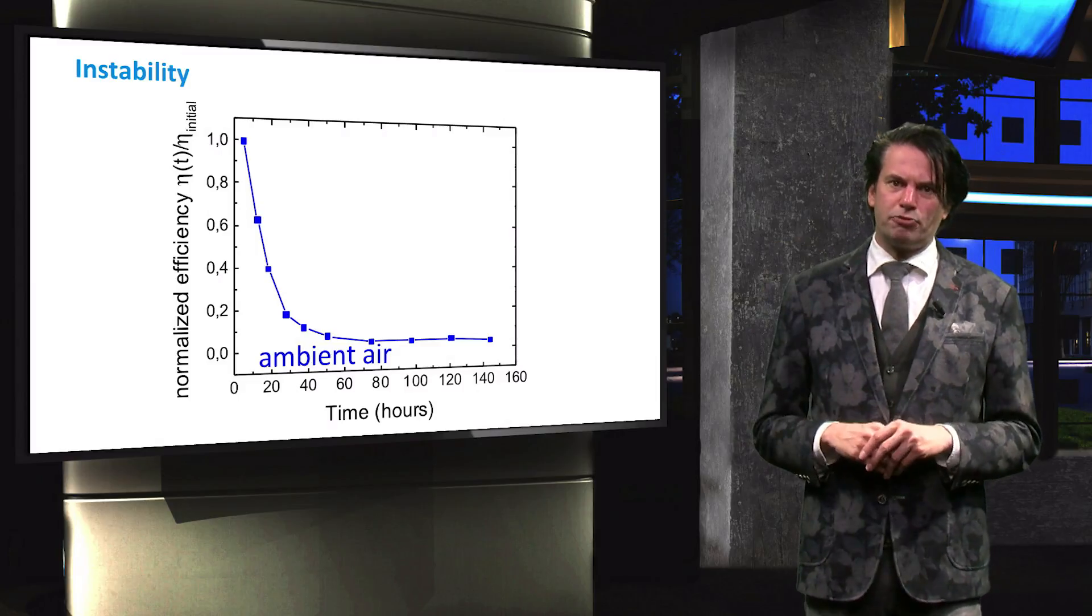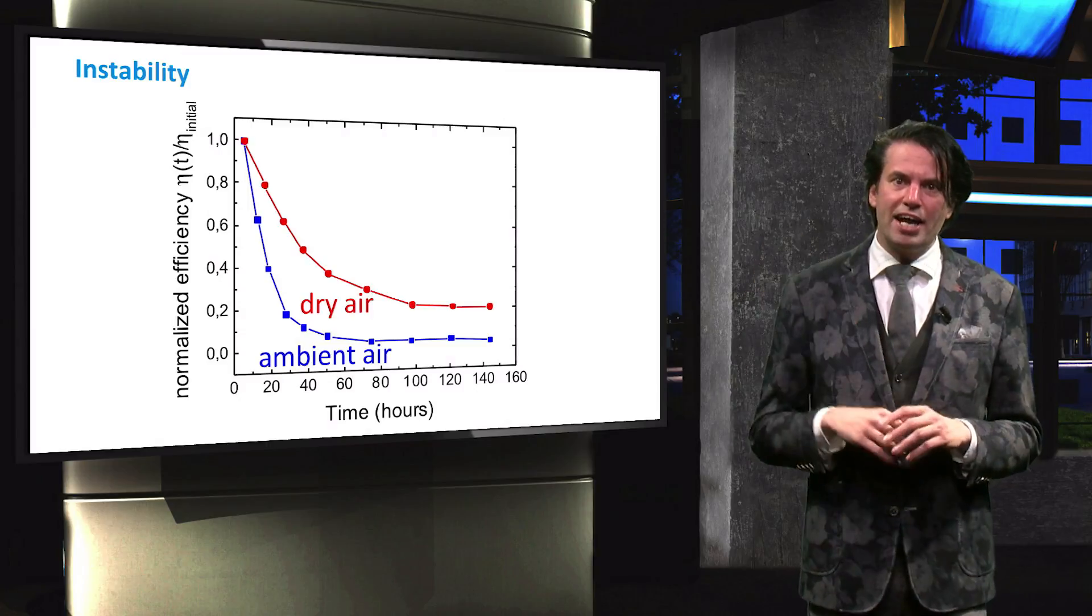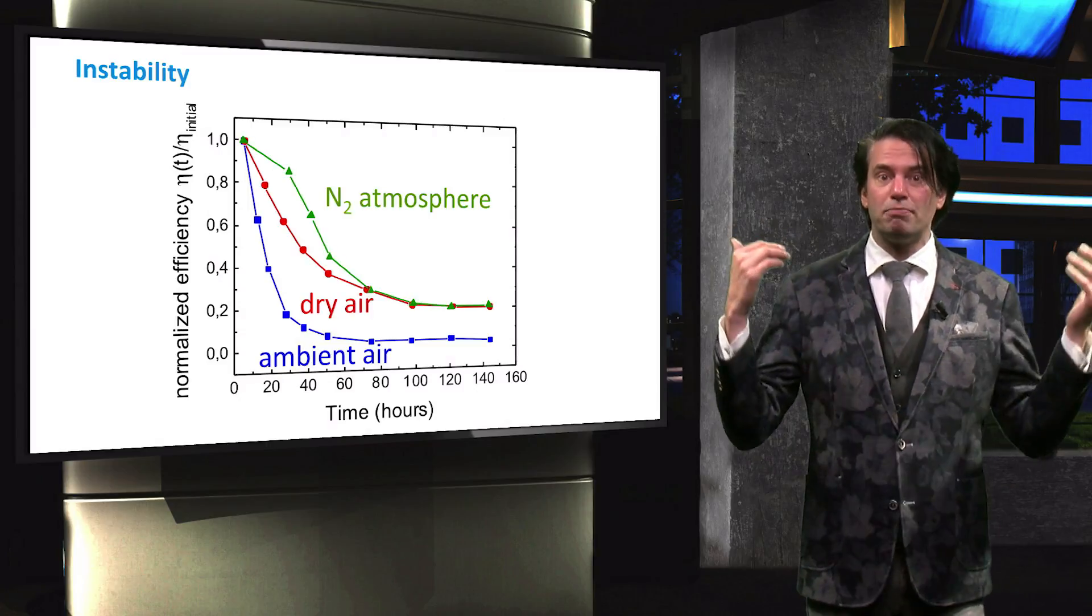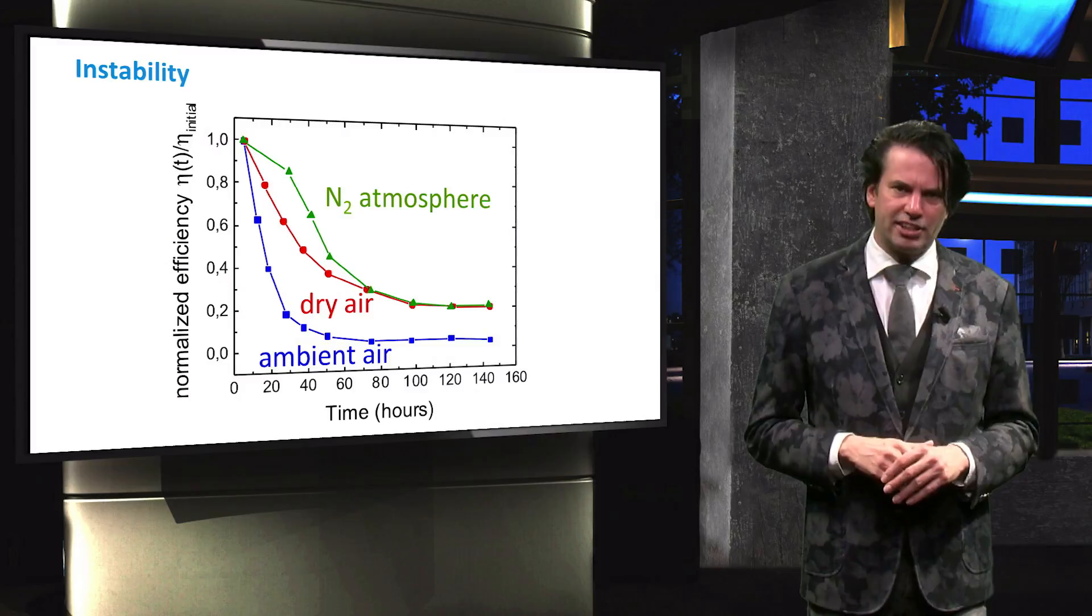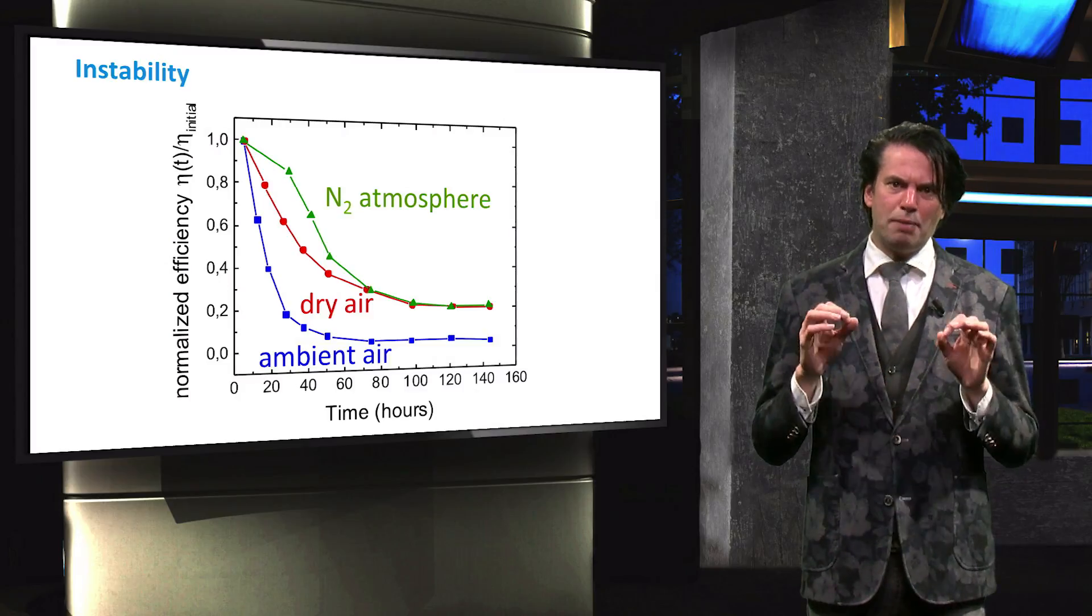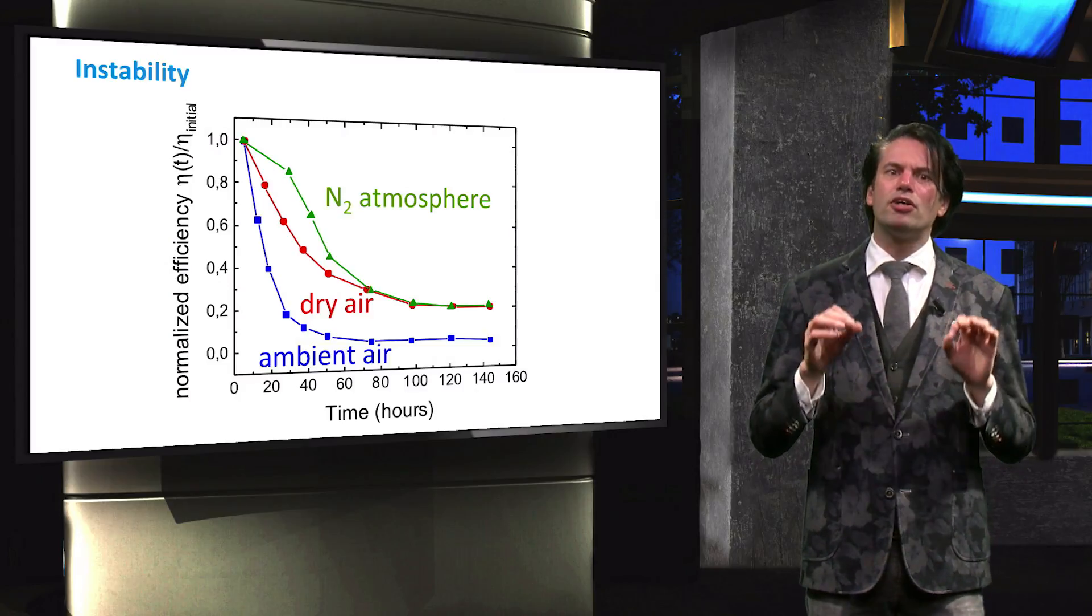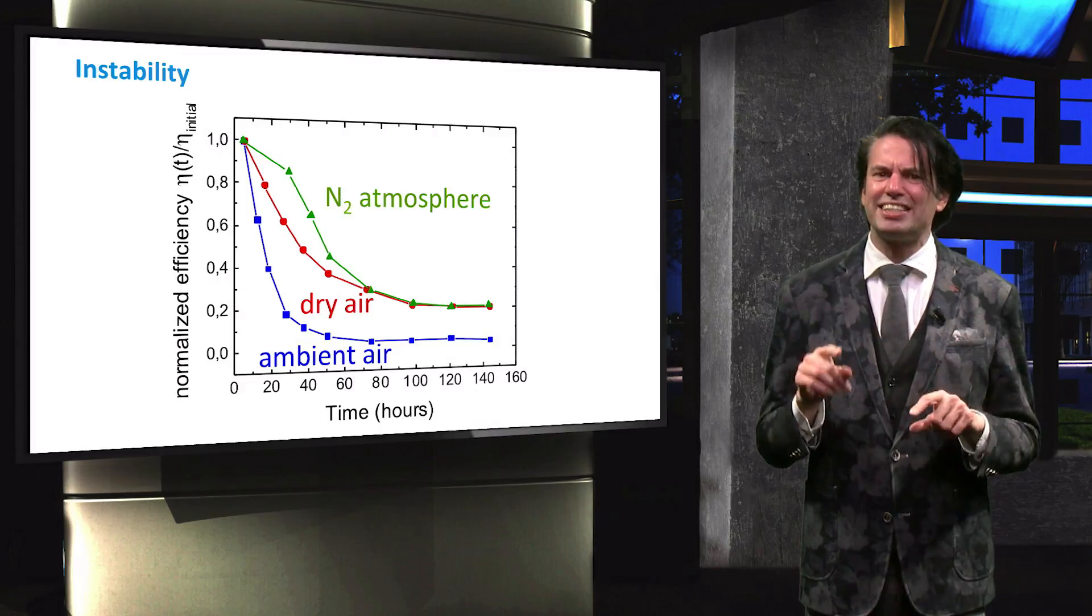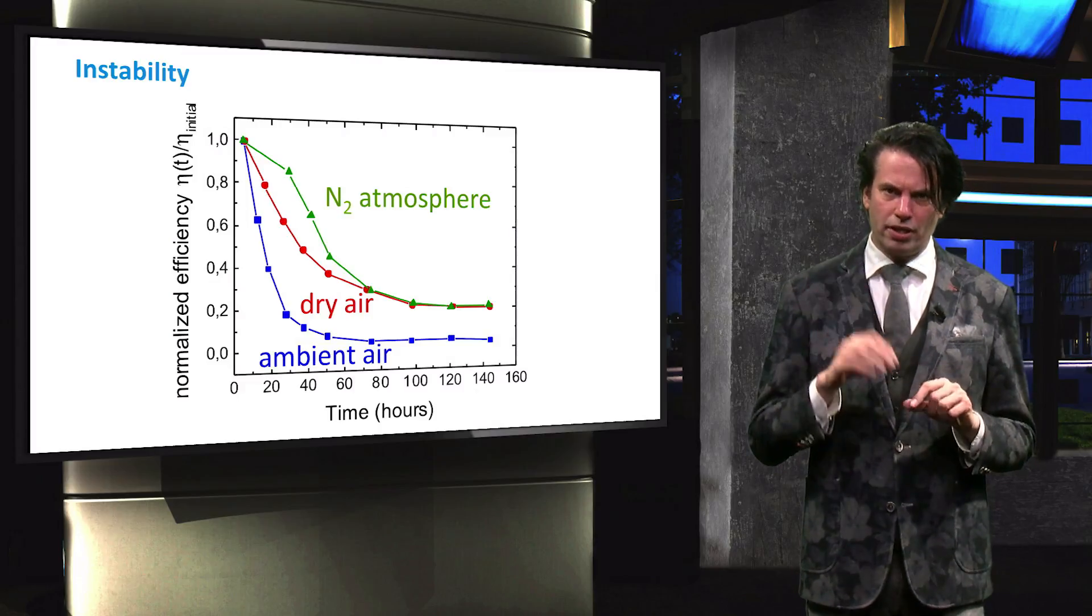If the same experiment is repeated here in dry air or in a nitrogen atmosphere, the degradation is delayed. This demonstrates that humidity plays an important role and suggests that the effect is a chemical instability.